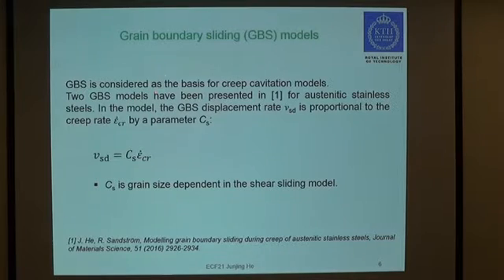Grain boundary sliding is considered as the basis for creep cavitation models. Two grain boundary sliding models have been presented for austenitic stainless steels, where it is related to the creep rate by the parameter Cs. This is the equation. The parameter Cs is grain size dependent in the shear sliding model.